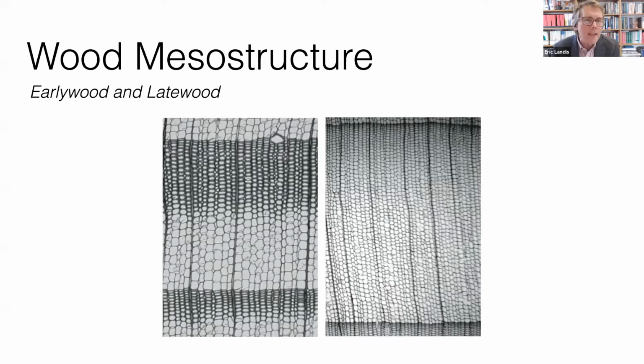And the reason we have rings, and rings are more pronounced in temperate areas where we have more variation in season, is that the tree does not grow at a constant rate through the year. In the spring and early summer, it grows very quickly, and then you get these very large cells with thin walls, and this is referred to as early wood. Then later in the year, that growth rate slows down, and you get smaller cells that tend to have a thicker wall, and that we refer to as late wood. So early wood and late wood is what gives that ring structure.